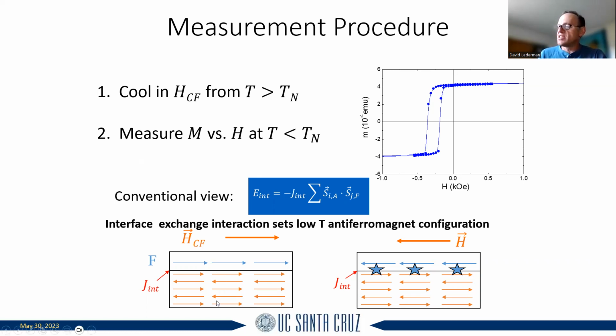So what happens is the antiferromagnet, because the net magnetization is zero, doesn't respond to the magnetic field very much, whereas the ferromagnet tries to respond because it's got a huge magnetic moment, and when it does so, it creates essentially, all of these bonds, all of these exchange interactions are frustrated, and that's what causes the exchange bias. Of course, this is a simple view, and there's a lot more details that need to be figured out because of the issues with real samples having a compensated surface and disorder.